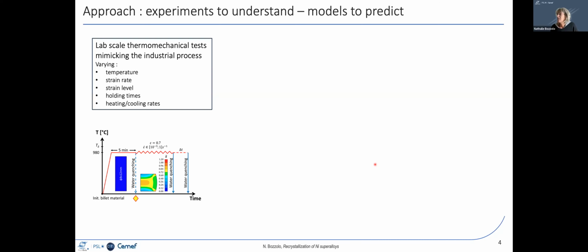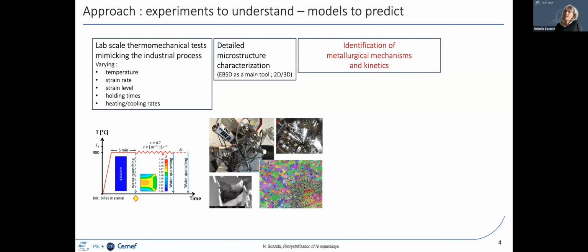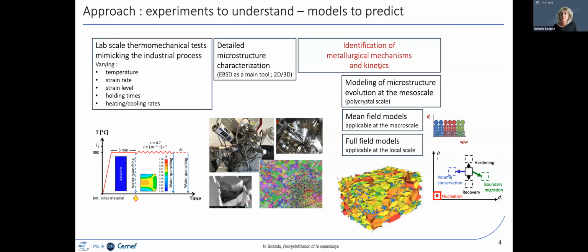How do we handle this at the lab scale? At the lab scale, we perform thermomechanical tests which mimic the industrial process, where temperature, strain rate, strain level, holding times, and heating and cooling rates can be varied to approach industrial conditions. Then, the tests can be interrupted at different stages and the microstructure characterized, so that the metallurgical mechanisms can be identified as well as their kinetics, which can then be described in different types of models.